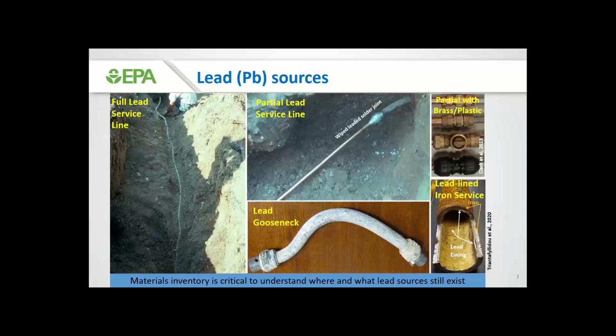We may have full pure lead pipes, 100% leaded materials still in service, such as the full lead service line on the left photo. We may also have partial connections where the public portion of the lead service line has been replaced with copper pipe, like in the photo in the middle top. You can see the remainder section of the thicker lead pipe still in place on the private side, and a wiped leaded solder connecting the 2 dissimilar metals. This is kind of an older way to connect new copper with the remaining lead.